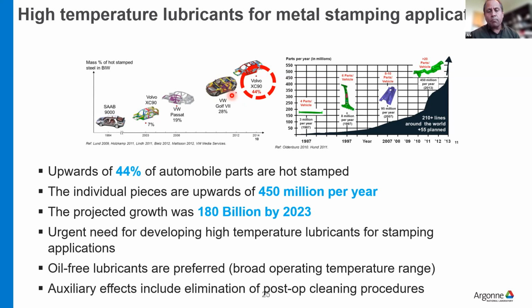Now, why does stamping need a lubricant? When you're making a shape of a certain size, you need to pinch the metal so the metal gets thin. But in the absence of a lubricant, the thinning will be uneven, and that gives rise to uneven mechanical properties. So in case of a crash, the tear will happen where there's an unevenness or a defect. That's why they use different kinds of lubricants, so that even thinning is possible all across the chassis without the formation of any defects.